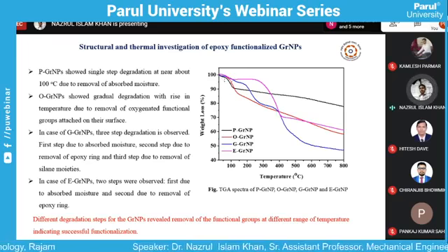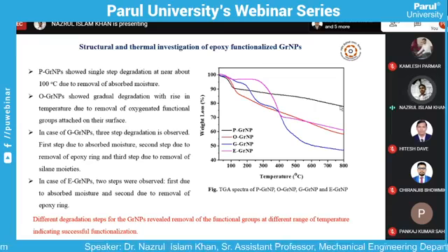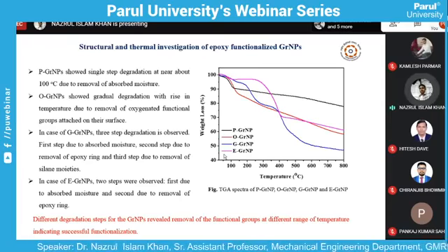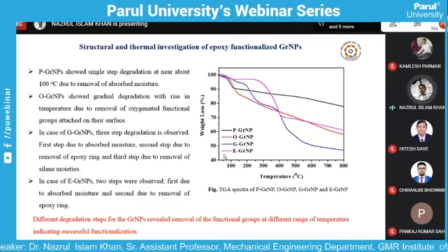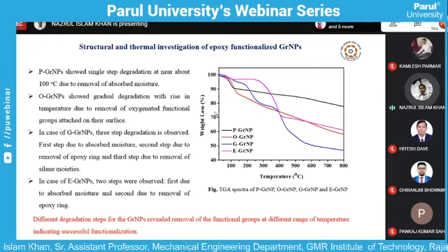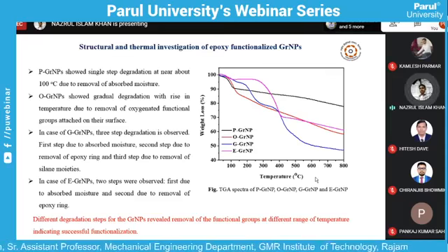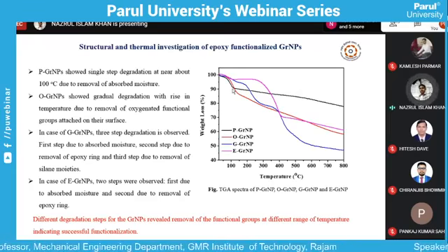If you see the carbon particles here, near about 100 degrees, one simple one-step degradation can be seen. This step degradation is mainly due to removal of moisture present, because you cannot keep any substance moisture free - if kept in air, it will definitely absorb some moisture. Since water evaporates near 100 degrees centigrade, we conclude that this degradation near 100 degrees is due to removal of absorbed moisture.